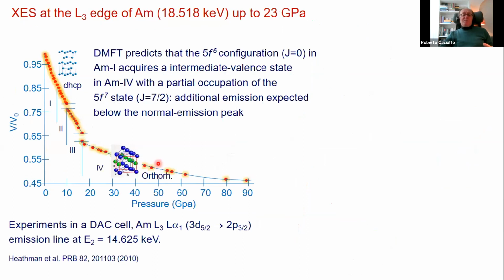RIXS experiments or beta X-ray emission experiments have been performed also at the L3 edge. In this case, in the case of americium, for instance, the incident energy is of the order of 18 keV. This then is a really penetrating probe. The experiment was performed in a diamond anvil cell to verify a prediction of dynamical mean field theory concerning the appearance of an intermediate valence state in americium-4.